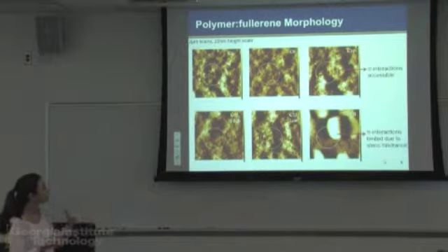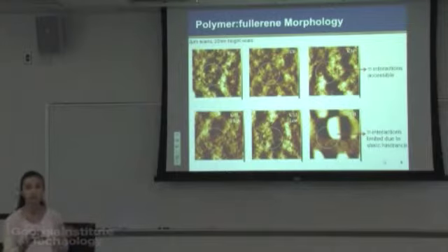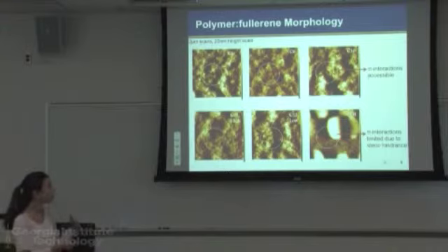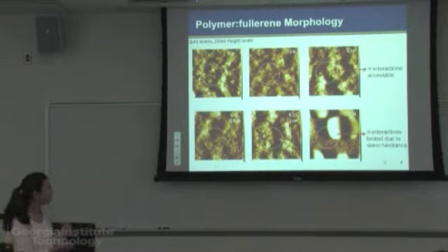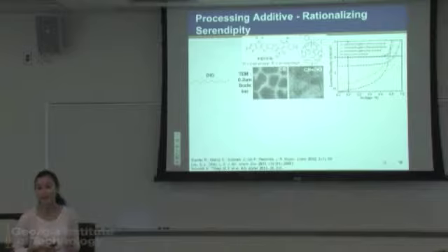And so what we outline is that when pi interactions between the polymer chains are made accessible, we can get to this fine phase separation. But when we hinder the pi interactions by having these torqued backbones that are induced by the sterics of the side chain, then we're allowing the formation of these PCBM aggregates, and that then dictates the morphology in the thin film.